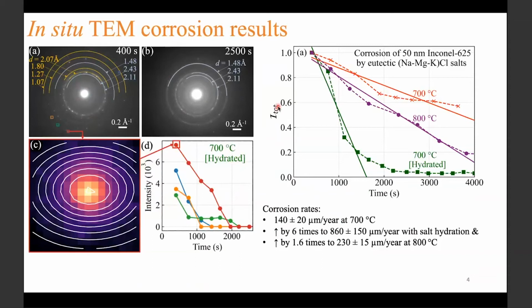shows the total intensity with corrosion time for some other corrosion experiments at different conditions. Here I have compared the corrosion in presence of water, which is hydrated, and absence of water, which is the top two plots. So here I have measured a 6-fold increase in the corrosion rate with hydration, indicating that corrosion rate is very sensitive to water. And I have also observed a 1.6-fold increase in the corrosion rate with increase in temperature, suggesting the corrosive effects of high temperatures.